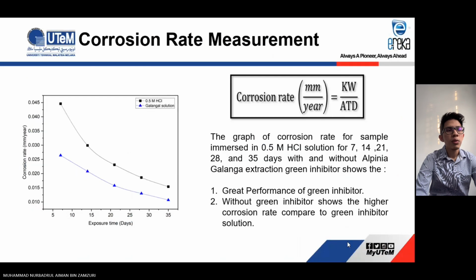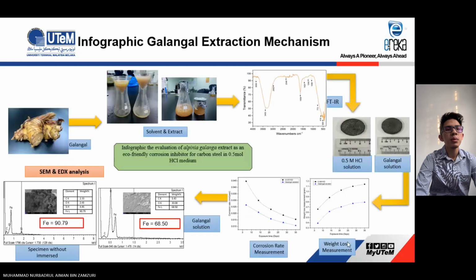Next, for the corrosion rate measurement, the obtained data shows the great performance of green inhibitor, and without inhibitor shows the higher corrosion rate compared to green inhibitor solution. And then this is the infographic that shows the evaluation of the technique of Alpinia galanga extract as an eco-friendly corrosion inhibitor for carbon steel in 0.5 molar hydrochloric acid medium.